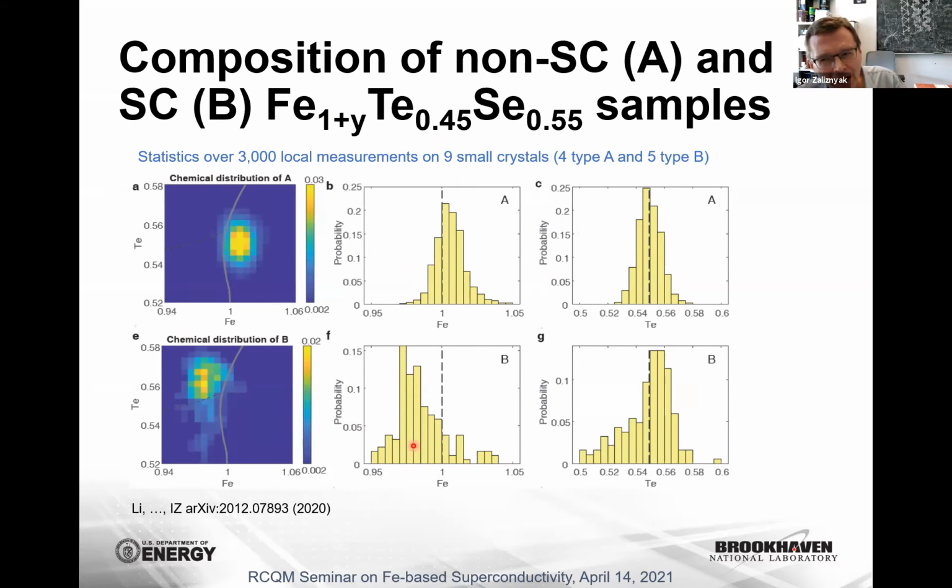Of course, we are not 100% sure that it's 0.98. It might be 1.01, maybe 1. The absolute accuracy of our measurement, EDS, is not so great. The relative accuracy is very good. What we can tell you for sure is that the composition of this one is just 3% different from the composition of this one. To that accuracy, determining from a diffraction experiment either vacancies or interstitials on the level of 1% is, I don't think, feasible. So we don't know.